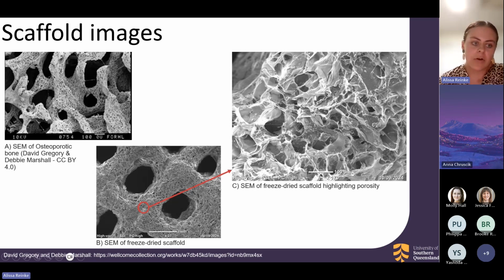So this is an image of osteoporotic bone, so there should be more bone here than there is. But looking at the general structure, you can see that this looks more similar to my scaffold than the previous one. And when we go in at a higher magnification, you can actually see that the pores are interconnected to one another, which means that cells are going to find it much easier to colonize and move around in the scaffold and start using the calcium from the scaffold to begin growing. So this is something that we are going to be doing a lot more investigation on, but it was a nice finding yesterday morning.